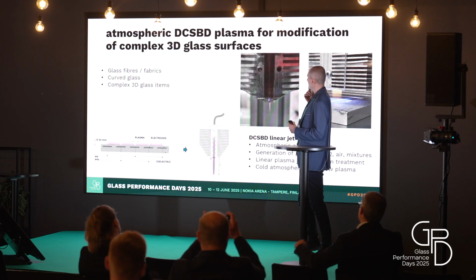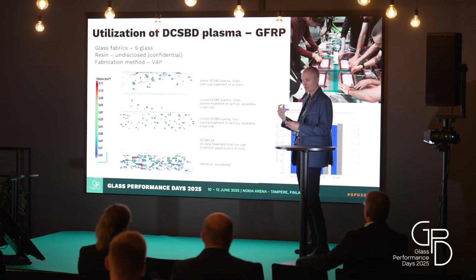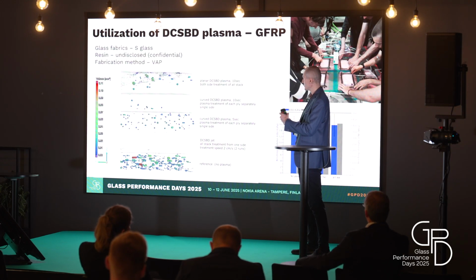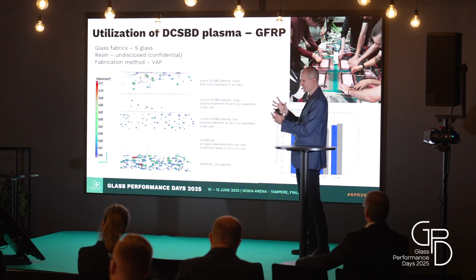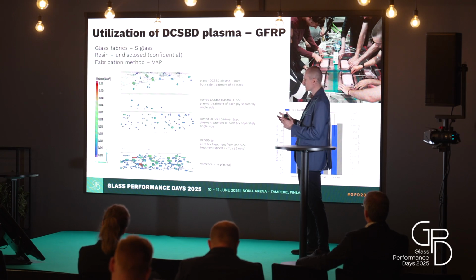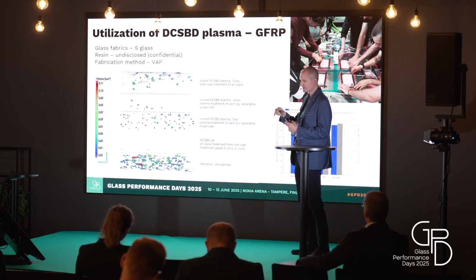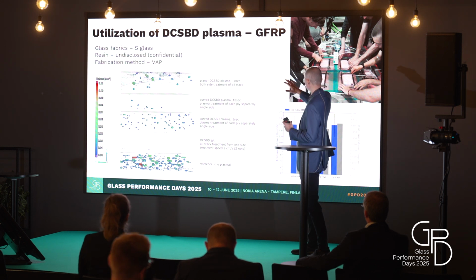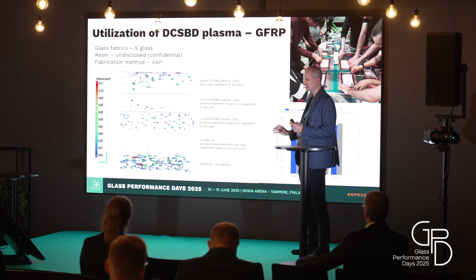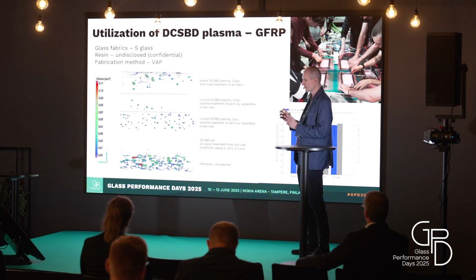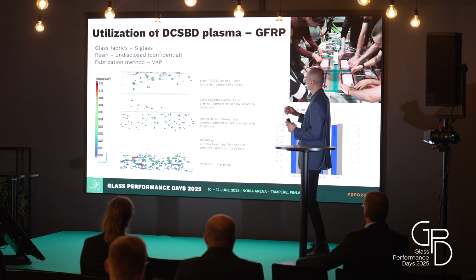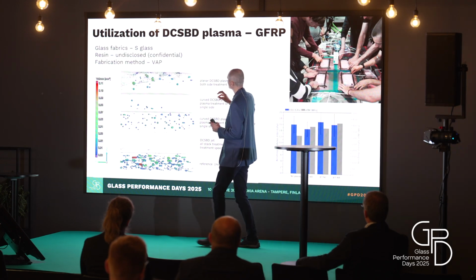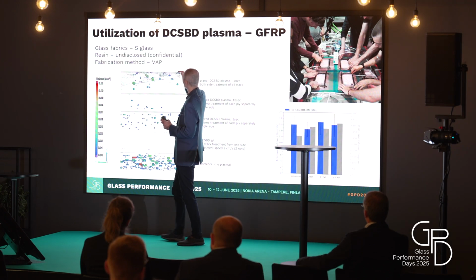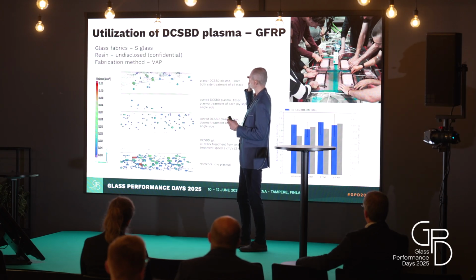And on the next slide, I just want to show you how plasma very efficiently changes the interface between the glass and some matrix or polymer when we create a composite material. For this, we use the micro-CT method for analysis. It's not very good for flat glass, so I decided to study glass fabrics and glass fibers. We created the glass fiber composite using S-glass fibers and some resin.